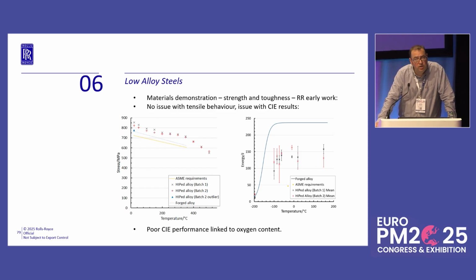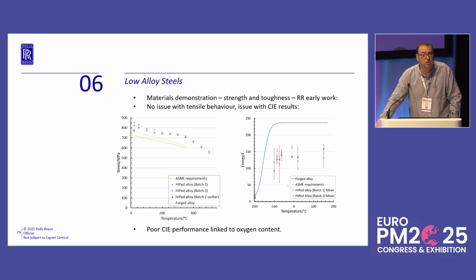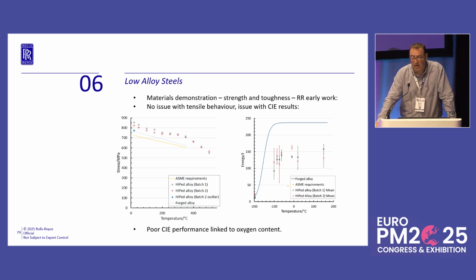The problem that we and everyone else had was with the Charpy impact energy data. And this gives us an indication of the toughness, and that's a really critical parameter for the nuclear pressure vessels. And unfortunately, we're not even close, and neither was anyone else. And everyone believes that it's down to the oxygen content that impacts the impact energy.